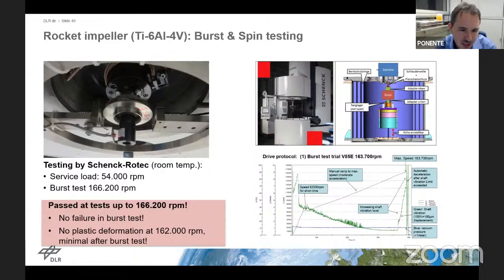And in fact, the parts have been tested by spin testing at a company. Burst tests at 166,200 RPM were successful. By design, this part should have failed at this rotational speed, but it actually didn't. And we even had only very minimal plastic deformation after the burst test. So we were kind of surprised that we actually did succeed in this project. None of us would have thought, given all the challenges in additive manufacturing, that we would actually succeed here.